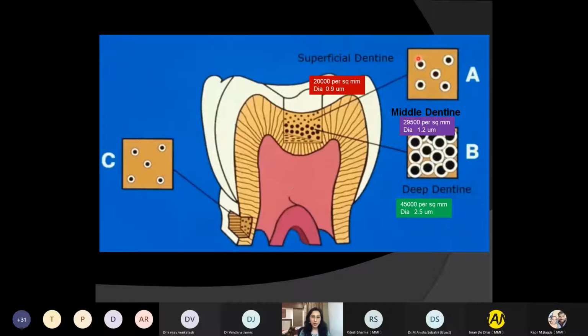Why is it so? It is because superficial dentine has dentinal tubules in the tune of 20,000 per square millimeter in number, and the diameter is 0.9 micrometers. And can you see, when the tubule diameter is less and there is less number of tubules present, so what happens? There is more amount of intertubular and peritubular dentine present for a good bonding to take place. In middle dentine, the number increases and the tubule number is 29,500, but the diameter also increases, which means that the peritubular and the intertubular dentine amount is lesser.